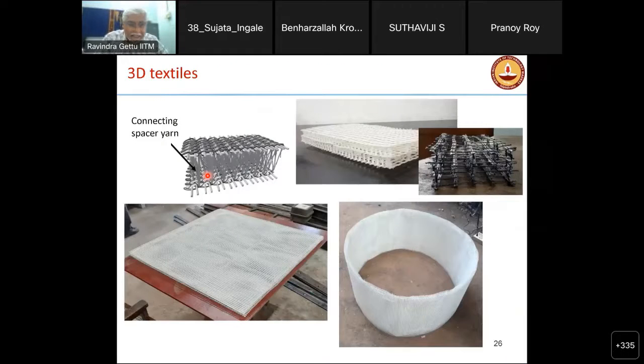Other cases we can think of are textiles which are three-dimensional. Instead of multiple layers, we can have a cage, just like we do for reinforcement in prefabrication. So what we did is we took multiple layers and put spacer yarns. So we made this 3D textile by ourselves with multiple layers. And then once you have it, we can just insert it into a mold. It could be circular, it could be square or planar. And then we can pour the matrix in.